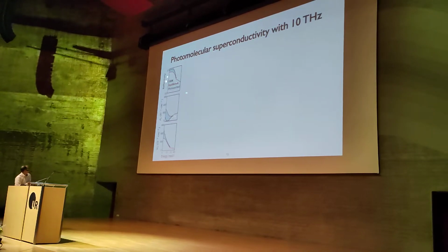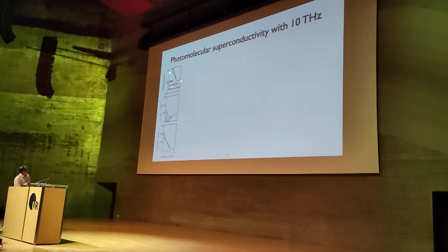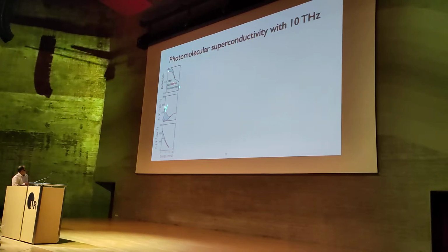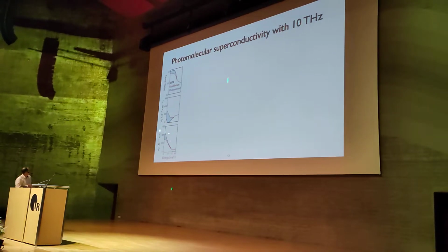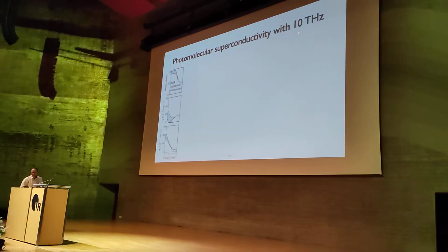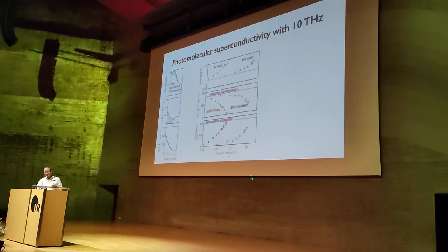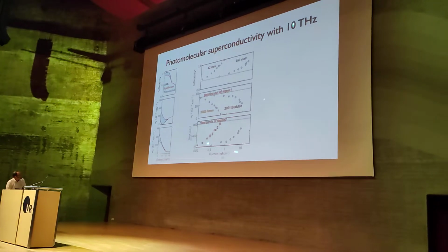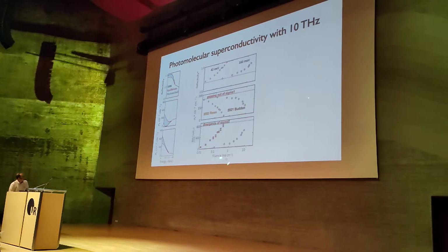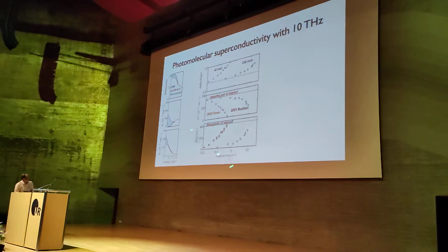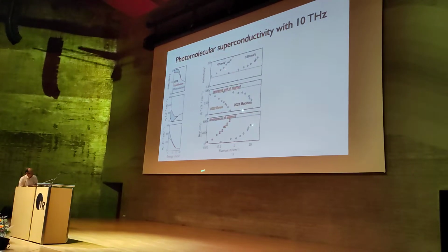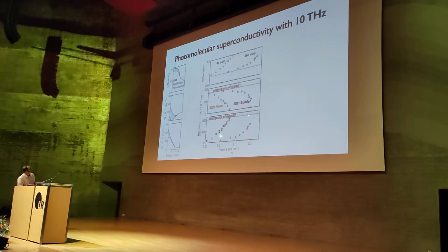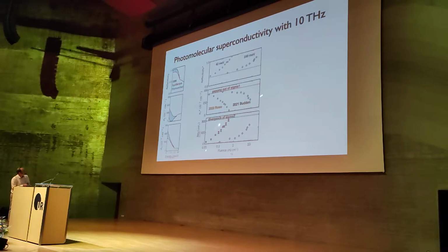They find at 100 Kelvin again, a situation where they increase the reflectivity to almost 1. They find this gap in sigma 1 and this depletion of spectral weight in the gap, and they find the upturn in sigma 2. So far so good. Now they can extract a measure of this effect, and more importantly, now they show this as a function of the pump fluence. So basically, the pump fluence that was needed in the old experiment is more or less the fluence of this one here, whereas the fluence that is needed in the new experiment is one,